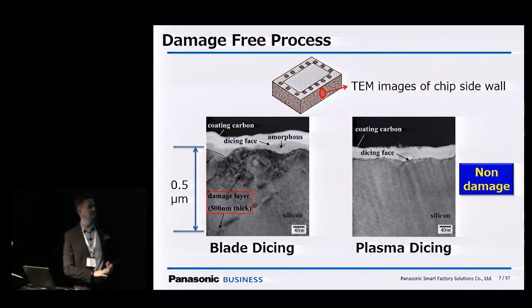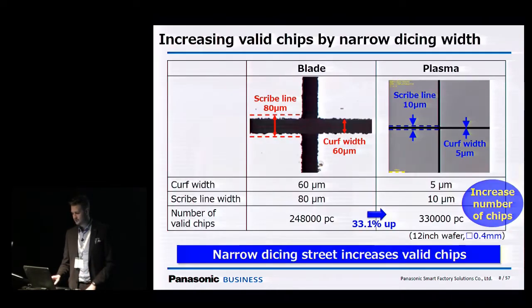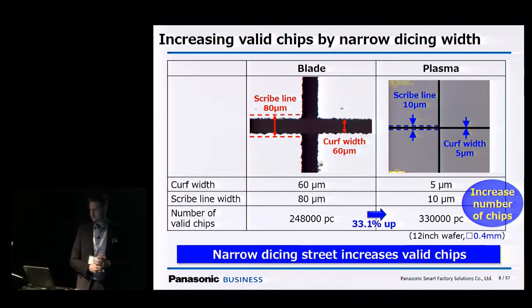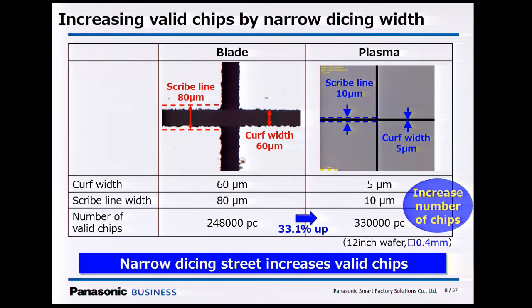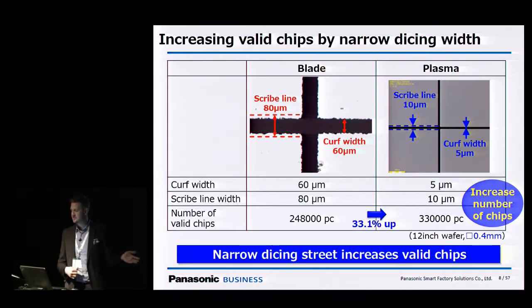Again, you can see on the left the damage in more detail caused by blade dicing, but plasma dicing on the right, completely damage-free. And if we go back to my example of wasting space, you can really increase yield with plasma dicing. On the left, you can see the thickness of the dicing street. I'm sorry, there's a spelling mistake in here. I should have fixed it. It's kerf, not kurv. The blade thickness is quite thick, but Panasonic plasma dicing can offer down to 10 or even 5 micrometer street width. So if we take this example in the table on a 12-inch wafer with a relatively small device of 0.4 millimeter, you can increase yield by 30%.